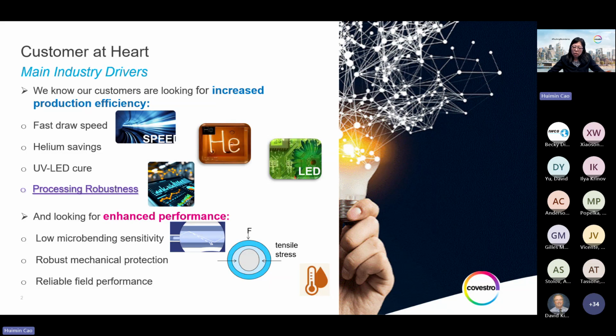the dual layer coating system, which is highly desirable for supporting the trend of reduced diameter fibers and for the fiber types of high microbending sensitivity, such as the large effective area fibers, or simply for supporting the ultra high density cable where the stress exerted on fiber is higher and higher.